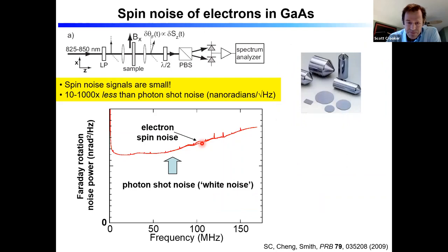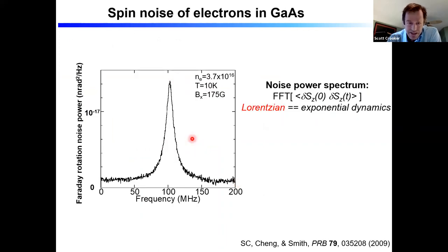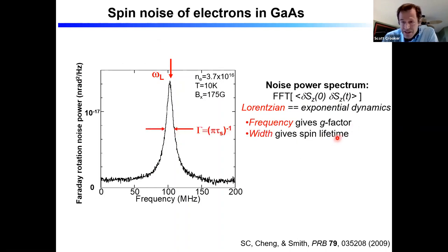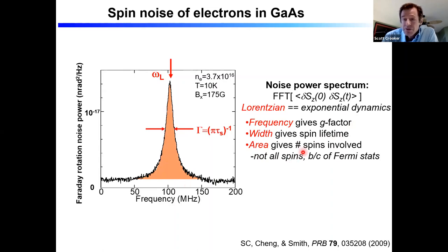So the key point here is that even though there's a relatively big background, by signal averaging, we can extract these noise signals very, very clearly. So again, this is an example of electron spin fluctuations in a semiconductor, and there's a lot of information contained in these noise signals. So first of all, for this case, the nice Lorentzian peak tells us that in the time domain, the dynamics are exponential. It's not always the case, by the way. The frequency, of course, tells us something about g factors. The width tells us something about lifetimes and dephasing and decoherence. And the area tells us something about the number of spins involved, which for fermions, of course, is not all of the spins. It's just those within kT of the Fermi surface.